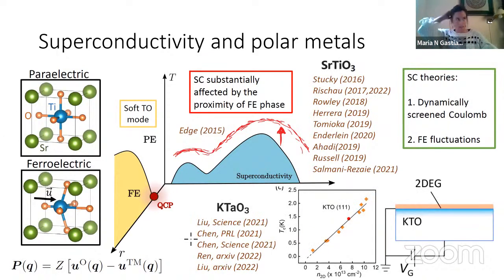And then to finish with the introduction of this arena of polar metals and superconductivity, there's also recently been another set of experiments based on a sibling of strontium titanate, that would be KTO. In this case, instead of being bulk, they make these heterostructures, or they can also dope the crystal with liquid gating. And in any case, what they find is that the two-dimensional electron gas that is formed superconducts, and it has Tcs that are much higher than measured in, for example, bulk STO. I'll explain a little bit at the end that there might be indications that a prominent mechanism for pairing in this system may be this direct coupling to the transverse optical mode.